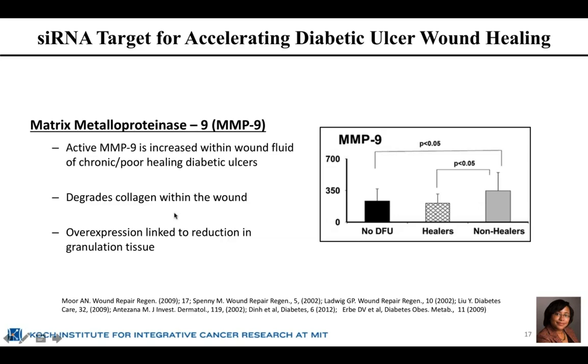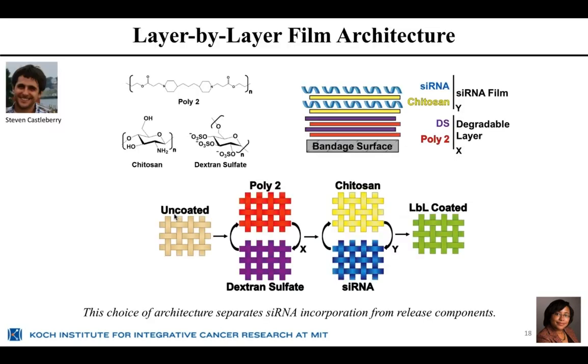So we actually incorporated siRNA to silence this MMP9 so that we could improve the wound closure process in diabetic patients. This is the work of my former student, Stephen Castleberry, and in this case, he coated layer by layer films that contain siRNA in alternation with a very simple and fairly common polysaccharide, chitosan, which is shown here on the left, has a positive charge to this primary amine and is derived from crab shells. Chitosan complexes siRNA very effectively, but it is not rapidly degradable. So he actually created an underlayer of a layer by layer film that contains the degradable poly beta amino ester, poly 2, and dextran sulfate, which is really a benign negatively charged polymer. This underlayer is meant to break apart and allow the release of the siRNA containing chitosan layer.